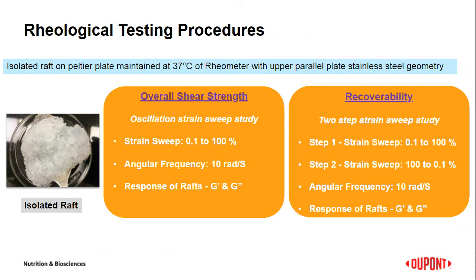So, the rheological testing procedure involves placing the raft on the lower Peltier plate of the rheometer, where the temperature is maintained at 37 degrees centigrade, and an upper parallel plate of stainless steel geometry is used for the testing. Using this isolated raft, we test two different experiments, to understand the overall shear strength of the raft as well as the recoverability of the raft. The shear strength of the raft is measured by the strain sweep method, where the strain percentage is increased from 0.1% to 100% and the response of the raft to the increase in strain is measured in terms of storage and loss modulus.